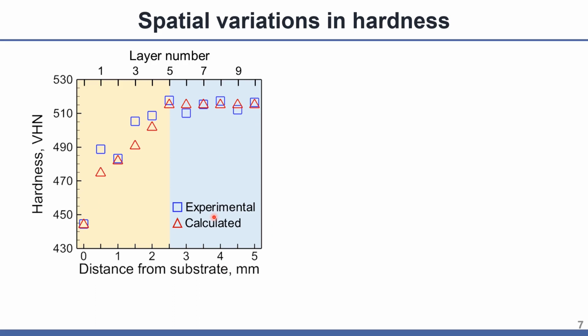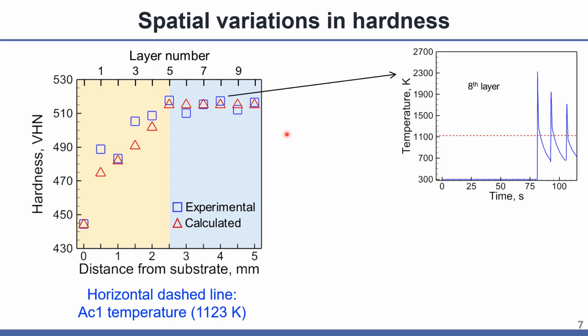It should be noted that the hardness increases with layers until it reaches a critical layer, layer 5, beyond which it remains almost constant. For the upper layers, for example, for layer 8, the peak temperature always exceeds the AC1 temperature. Therefore, the hardness of those later layers was almost unchanged because martensite was untempered after re-austenization.